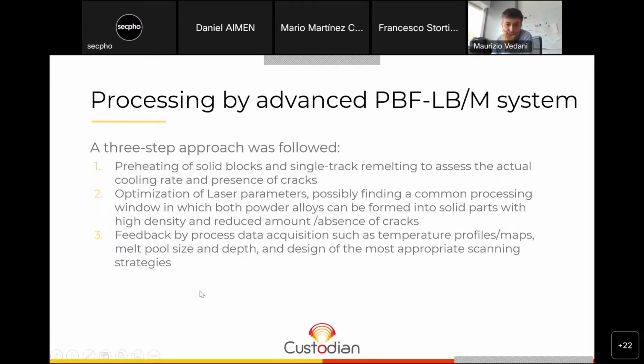So for this purpose, these are three of the tests that we carried out at the very beginning of the project. On the one hand, in order to obtain those optimal thermal cycles that Mauricio was describing, and that will help to mitigate this cracking issue during the processing of these alloys, we carried out the preheating of solid blocks and single track remelting of both materials to assess the crack presence and their different cooling ramps and the different cooling thermal cycles. So with these experiments, the main intention was to define certain conditions where the cracking phenomenon was eliminated or mitigated, right?